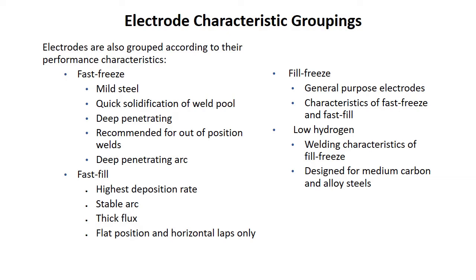And then low hydrogen kind of gets dumped in with the fill freezes because the pool will freeze on you, but not as quick as a fast freeze, but you also have the ability to deposit some weld metal into the weld joint at a reasonable rate that is a little higher than what you would get with a fast freeze or a 6010 type electrode.